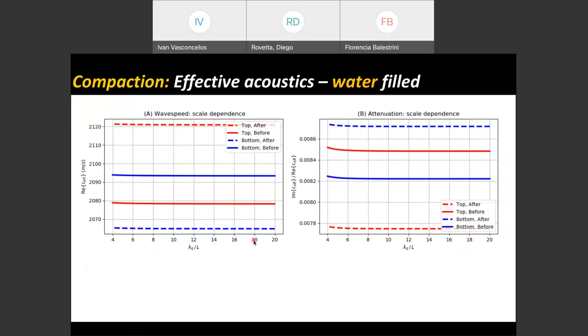Now notice what happens to wave speed. At the top, wave speed increases. Yes, on the top, sorry. This is the top before, this is the top after, and wave speed increases. So it should, because you've crushed the pores, and the pores are more compliant than the matrix. So wave speed has to increase. At the bottom, porosity increased, if you remember, so wave speed decreases. So this is purely due to changes in volume fraction.